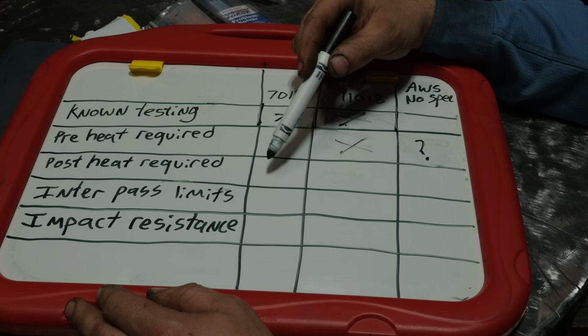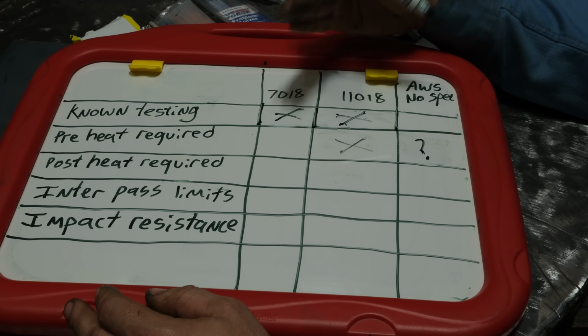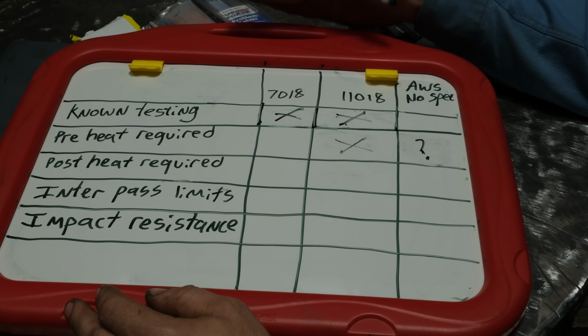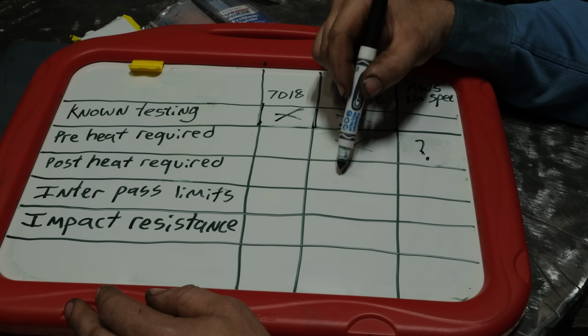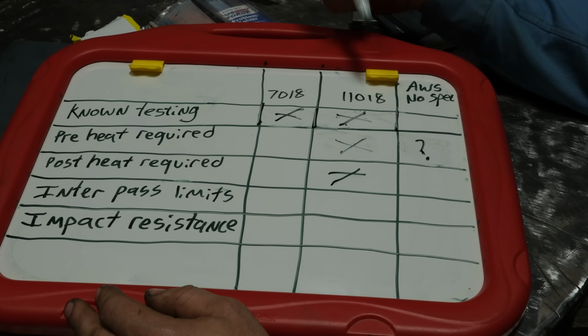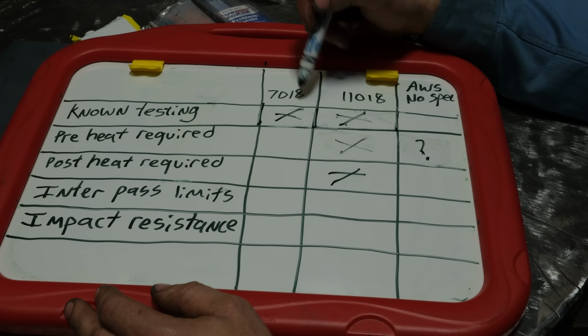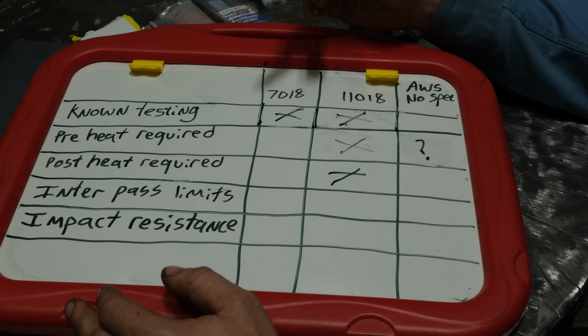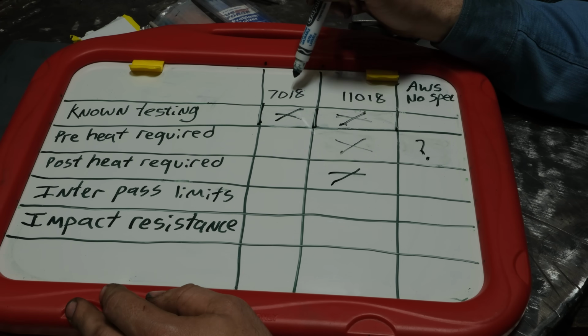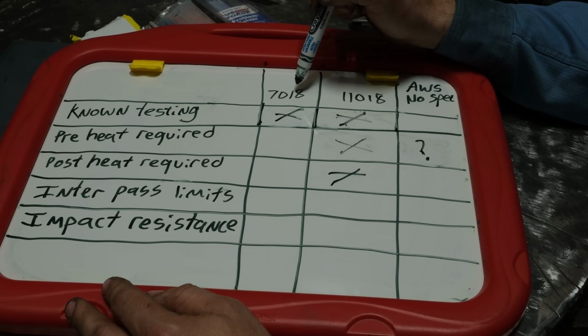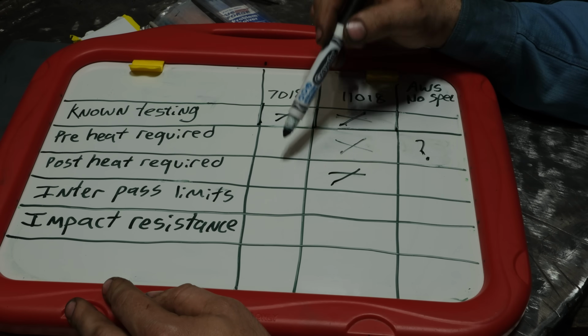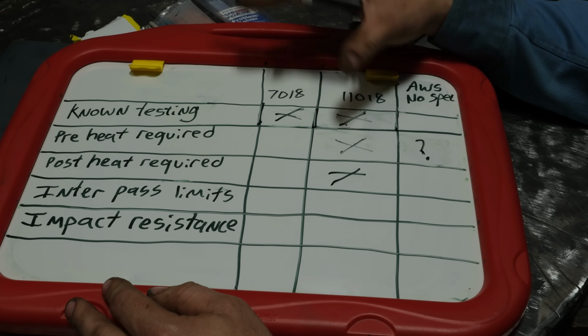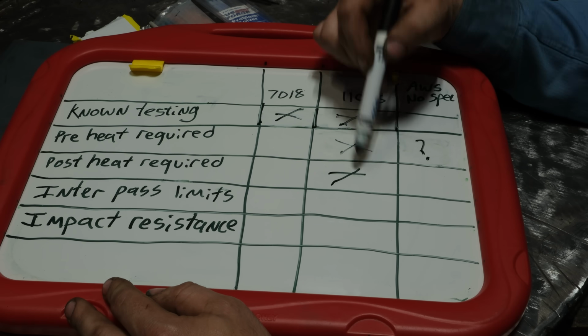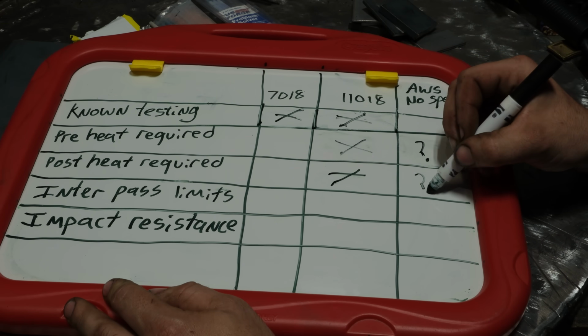So that's not good. Now, post heat, which is basically keeping what you welded warm for longer and slowly cooling it. Post heat can be required with higher strength steel as well as when you're welding with 11018. 7018, generally speaking, for anything you might do, not really required. However, if you saw my previous video where I water quenched a 7018 weld, that made it extremely brittle and it failed during a bend test. So cooling it rapidly isn't good, but just letting it air cool, however fast it does, isn't a detriment for that. It is for this. Now, again, non-AWS spec, who the hell knows?